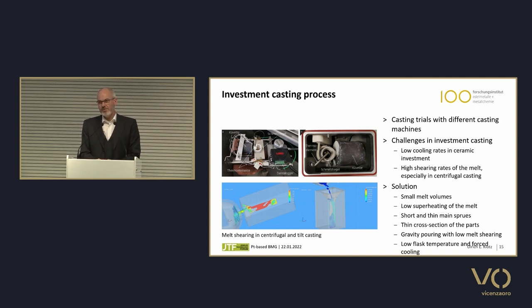Why did we do so? Because you have to prevent the crystallization. There are impurities, there is the high cooling rate, but there is another factor, which is the so-called shearing of the melt. When you cast the melt in centrifugal casting, you have a high shearing rate, and this shearing rate is plotted in red. This is the shearing rate during filling. You see that it's quite high during centrifugal casting and quite low during tilt casting,